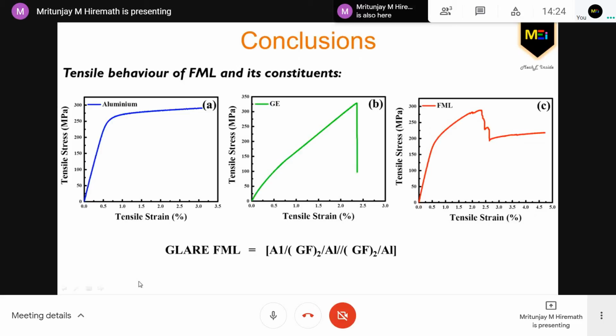So coming to some conclusions and the results, you can see a typical constituent behavior, specifically the aluminium and the glass epoxy composite, wherein aluminium being ductile in nature exhibits a ductile behavior, whereas glass epoxy composite being brittle in nature will initially exhibit a linear stress-strain response, but then it fails catastrophically. When we combine these two constituents, we get a specific stress-strain response of a fiber metal laminate, and we can see there is a sudden drop whenever the stress-strain response was plotted for the fiber metal laminate.